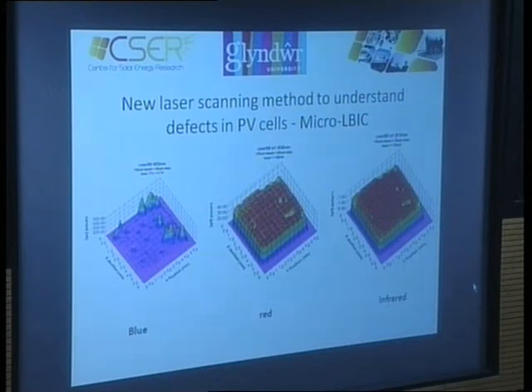One of the research students, Will Brooks, has developed a technique where he scans a laser across the surface of a complete device, at three different wavelengths: blue, red, and infrared. Now it so happens the blue will absorb in the cadmium sulfide layer, so it shouldn't actually get through to the cadmium telluride, but the peaks there show that in places it is. And we've gone on to show that this is because in those regions, that window layer is actually very thin.